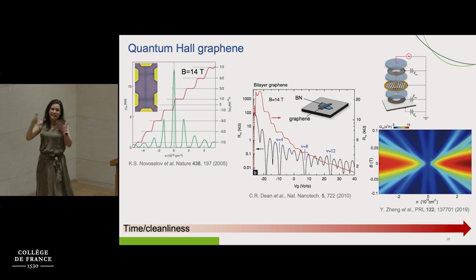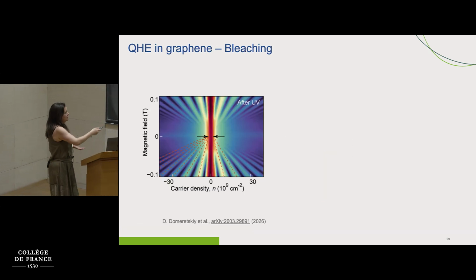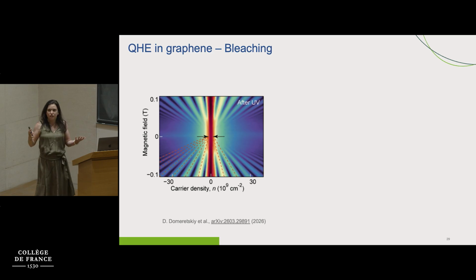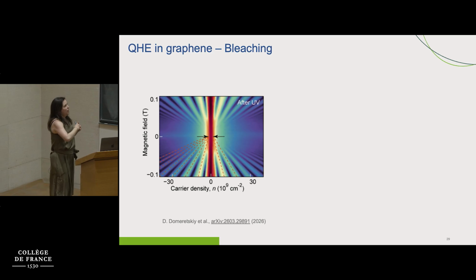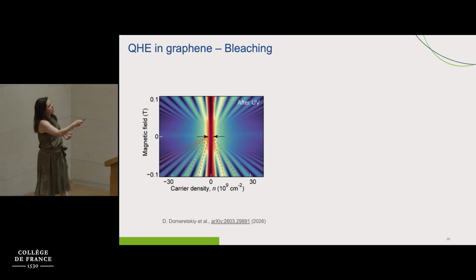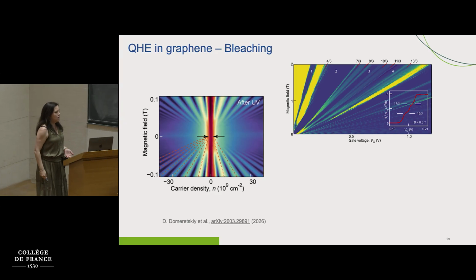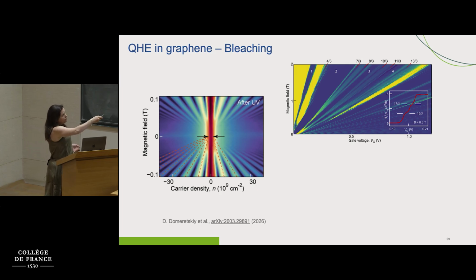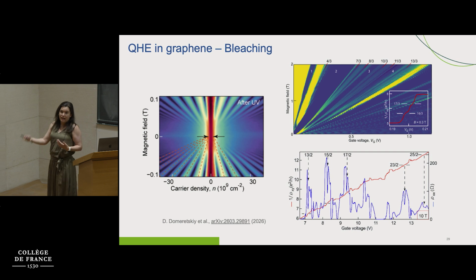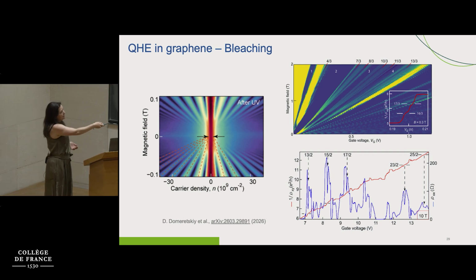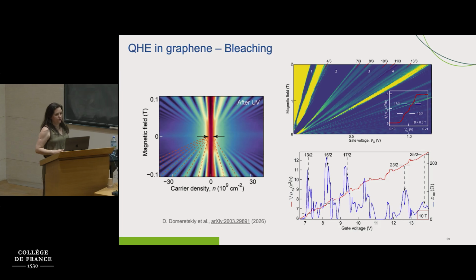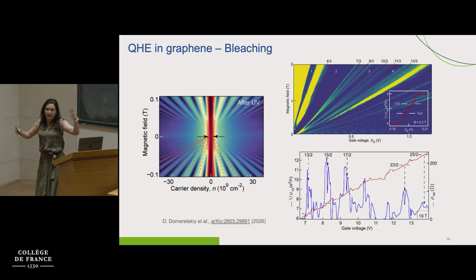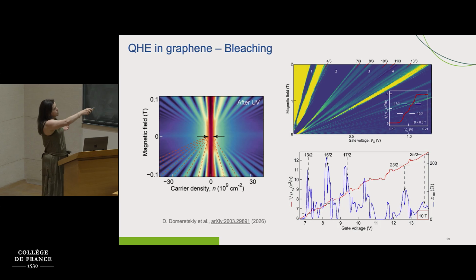So today the cleanest devices were in fact recently measured with a new technique called bleaching, where at low temperatures you are able to bleach the defects in boron nitride and get even cleaner materials. So for example, here you can see that the magnetic field at which you can obtain the integer quantum Hall effect is very low. The same happens to the fractional quantum Hall effect, at a very low magnetic field, and you can observe electron solids, also at a very low magnetic field compared to what was observed before. And this is graphene, perfect. So we have the three landmarks that I showed you before: integer quantum Hall effect, fractional quantum Hall effect, electron solid states.